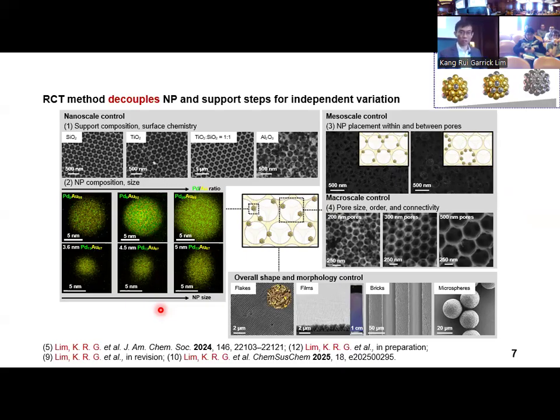Yeah, absolutely agree with you. So the question is whether the facets and the shapes, the faceting of the nanoparticles, can be used as a tool to control and further fine-tune reaction performance, and that's absolutely possible. Many groups have done it, and in our way, we can do it too. I think it's more applied in electrocatalysis and photocatalysis, where the reaction conditions are not so elevated in terms of temperature and pressure, because at temperatures of about 200 to 300 C, and at high pressures, these surfaces are not as stable as you'd expect when you synthesize them, and they would restructure. So you see in the elemental mapping, they form a round, amorphous, non-crystalline or polycrystalline nanoparticle out of it. So it'd be very difficult to deconvolute the effects altogether. But it's entirely possible if you reduce the reaction temperature and use it for photocatalytic or electrocatalytic applications, you will be able to use shape-controlled nanoparticles, and some colleagues in our groups have also done it.